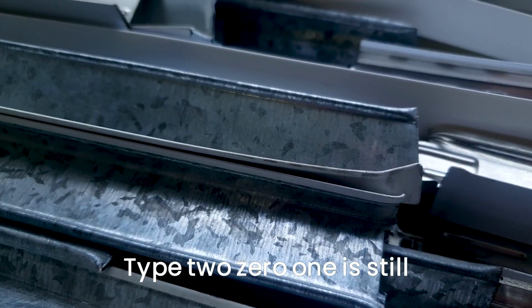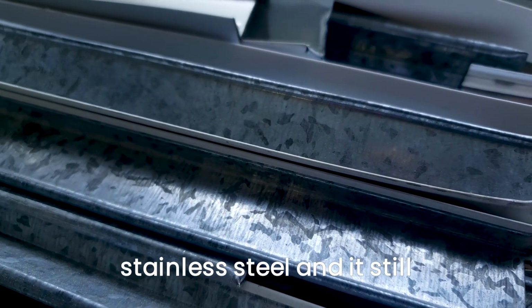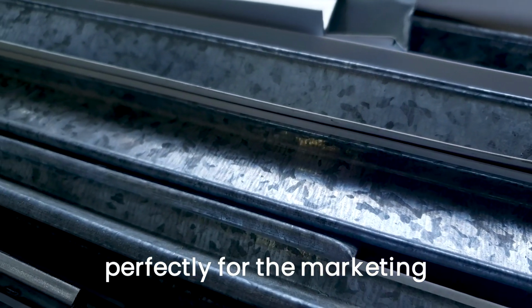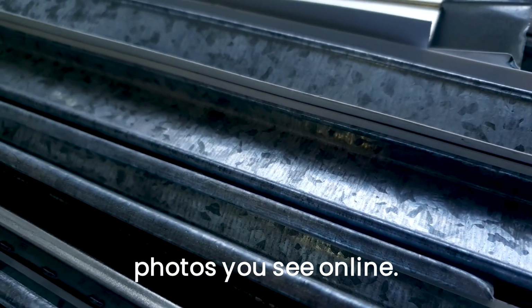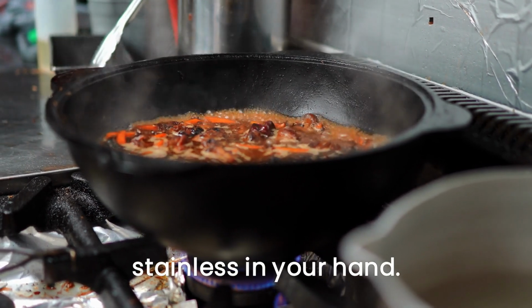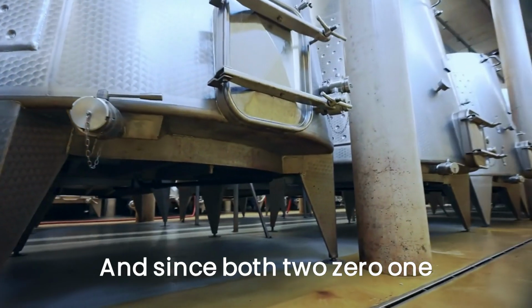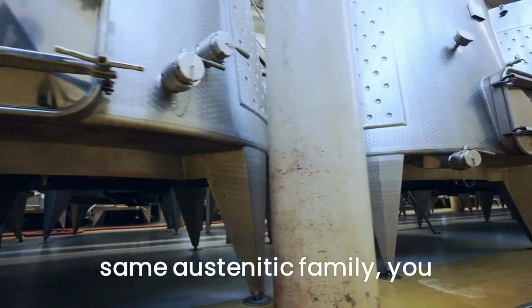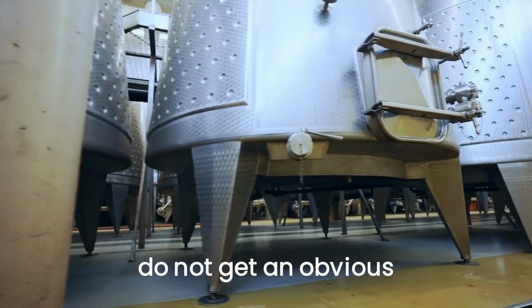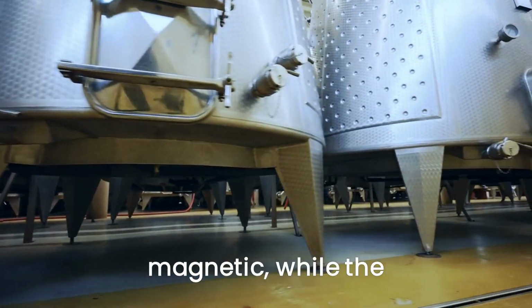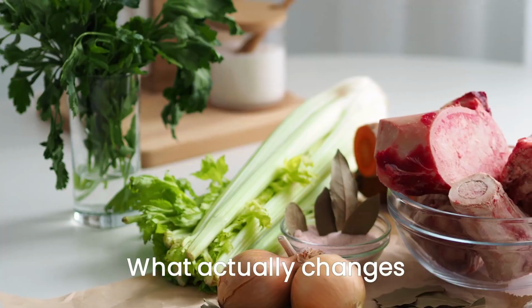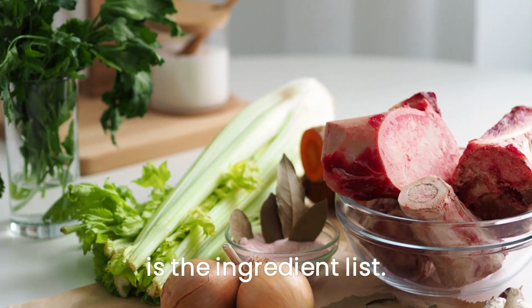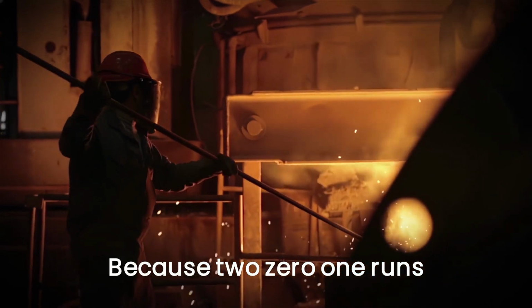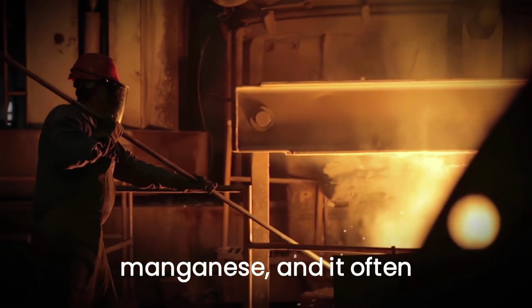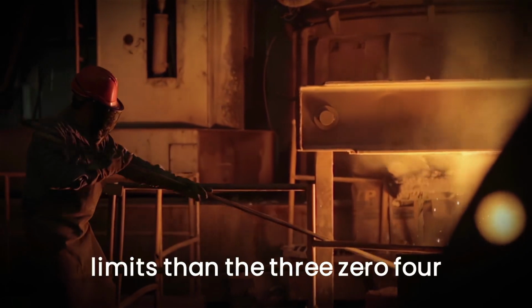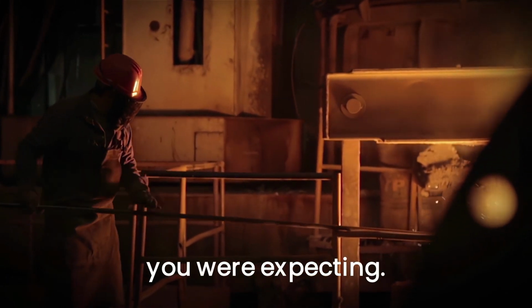Type 201 is still stainless steel, and it still shines and polishes up perfectly for the marketing photos you see online. It still feels like heavy stainless in your hand. And since both 201 and 304 live in the same austenitic family, you do not get an obvious giveaway like one being magnetic while the other is not. What actually changes is the ingredient list, because 201 runs with less nickel and more manganese, and it often carries much higher carbon limits than the 304 you were expecting.